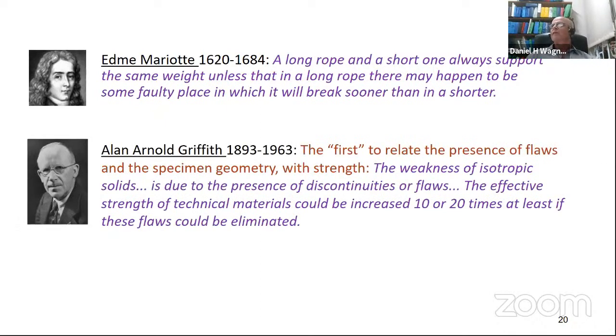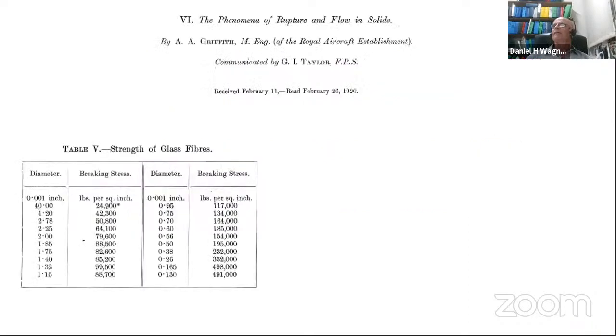And then came Griffith, of course, who was the so-called first, but actually Mariotte did it before, to relate the presence of flaws and the specimen geometry with strength. He stated that the weakness of isotropic solids is due to the presence of discontinuities or flaws. So he really assumed that there are always flaws in materials. And so he concluded that the effective strength of technical materials could be increased 10 or 20 times at least if the flaws could be eliminated. Of course, this is well known today. And so this is a first address of the size effect.